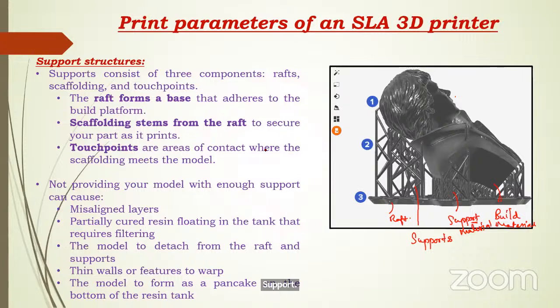Touch points are areas of contact where scaffolding meets the model. Not providing your model with enough support can cause misaligned layers, partially cured resins, and the model to detach from the supports. Once it cures thoroughly, this raft tends to cure thoroughly. It tries to stick to the build platform, and the removing of this raft plays a vital role. Thin walls are prone to warp the model, forming a pancake on the bottom of the resin tank. So careful selection of the support structure plays a vital role in case of an SLA 3D printer.